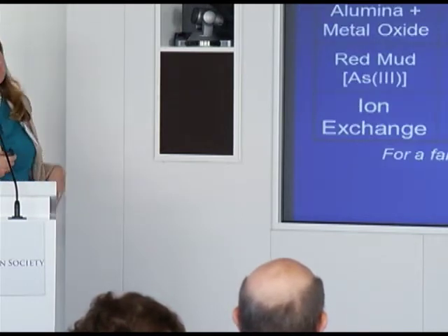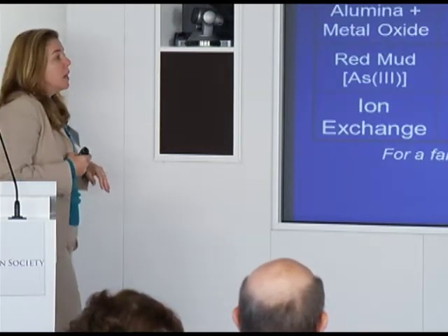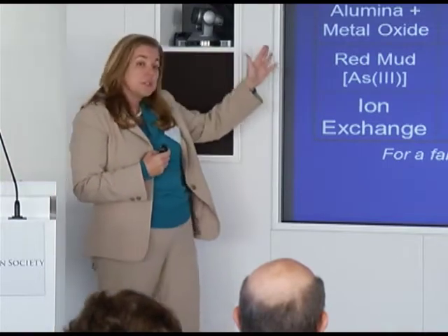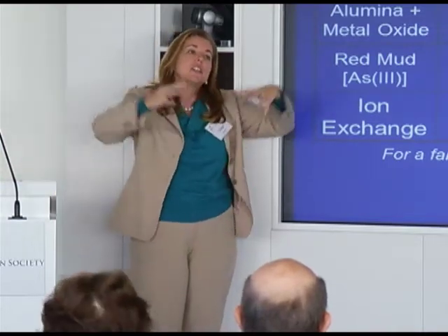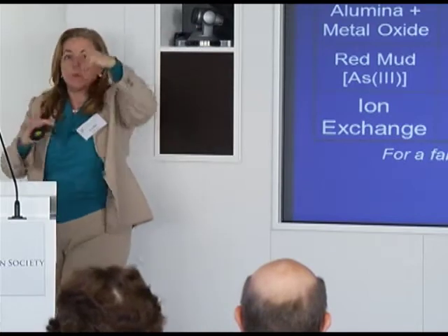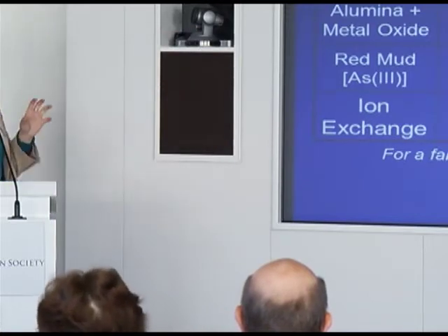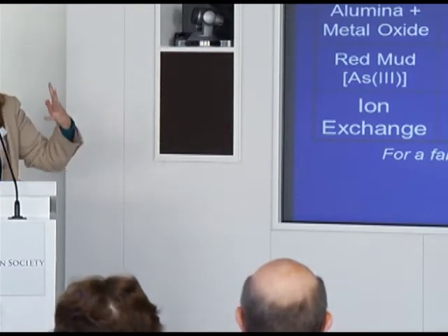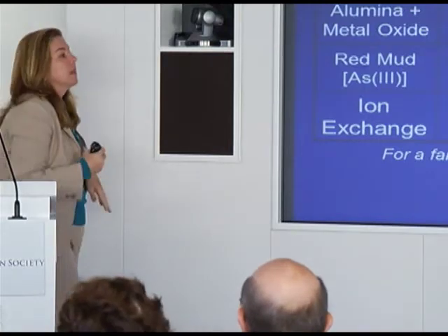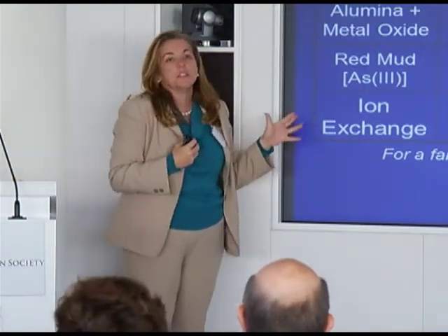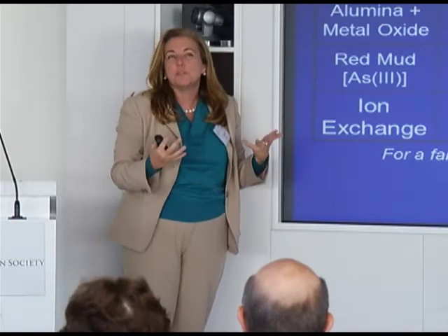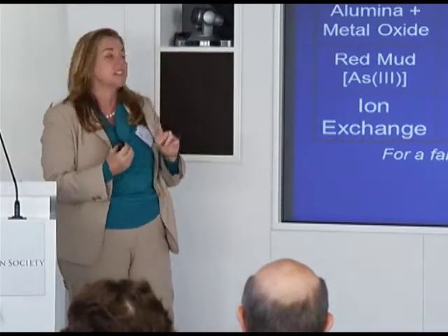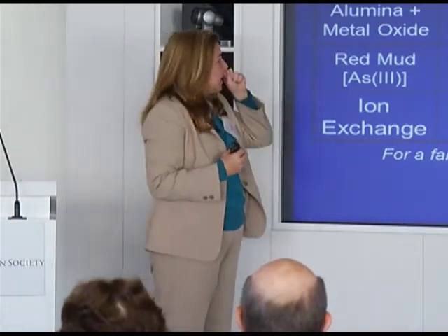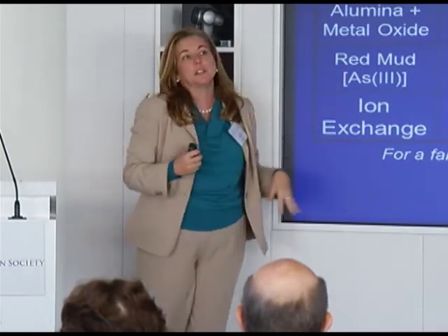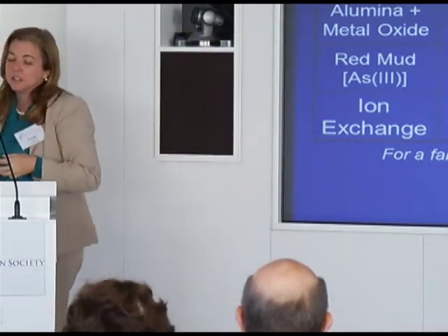These are some examples. I won't go through the technologies that are out there. But to make a long story short, the chemistry of arsenic, in solution it's actually an arsenate. Arsenic's in the middle with oxygens around it. And it's really, really big and diffuse and anionic. It's hard to get to stick to stuff. And so many of the existing technologies have been very poor, very inefficient. A lot of material, not a lot of arsenic stuck to it. But one that was getting a lot of interest was this red mud material, which is actually mine tailings, which has a lot of iron oxide.